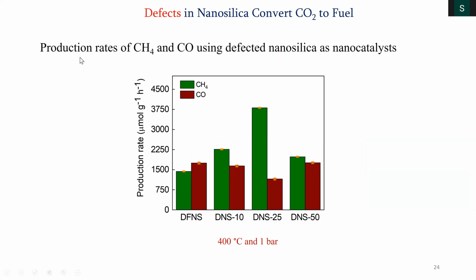And these are the catalytic results. So you see now DFNS, no defects. When I say no defects, all materials always have some defects. It's really difficult to get defect-free materials. But those natural defects are low in concentration. With 10, 25, 50% Mg, we increase those defect concentrations and create new defects. And you can see the methane yield is around 3750 micromole per gram per hour with DNS-25. With more increase in the defect concentration, the yield goes down. We will ask the question of why 25 is better.